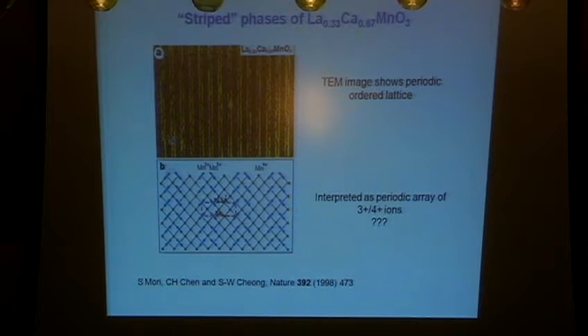The other thing, however, buried in the phase diagram of these materials are things like this. This is lanthanum calcium manganite with a lot of calcium in it. And this is an electron micrograph, a TEM image. And these lines that you can see are in fact lines of atoms showing some kind of contrast. And this contrast, and this is actually an insulating phase, was interpreted more or less correctly as stripes, charge localization of lines of atoms. And so this is a mixture of normally manganese 3 plus and normally manganese 4 plus. And if you orbitally and charge order the system so that some of the atoms are in 3 plus state, and some are in 4 plus state, you can produce a pattern which looks just like this.